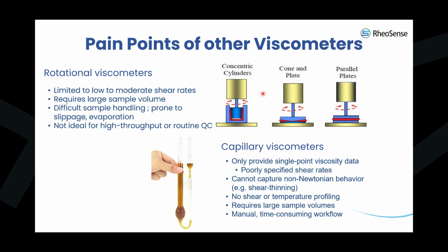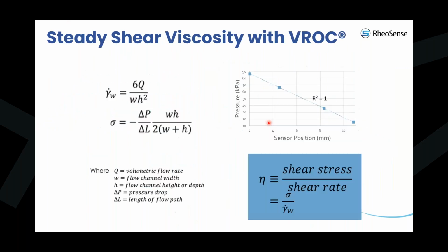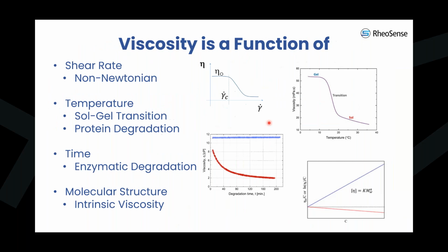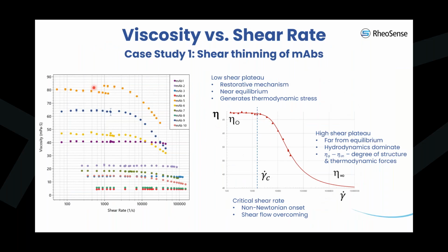Let me go to that slide to show you the graph here. We see that at low shear rates, we do not have any shear thinning. Viscosity is constant. But as you increase the shear rate, this shear thinning characteristic starts to appear. But in cone and plate measurement with protein sample, it will show the shear thinning from the beginning, from the very low shear rate.